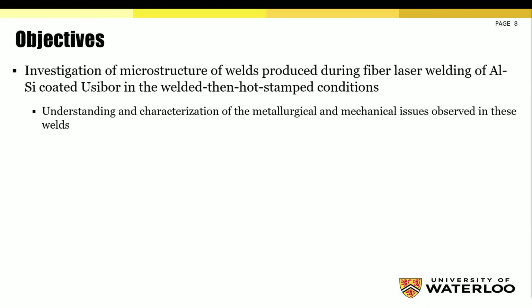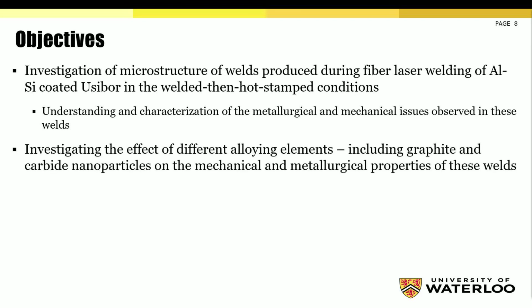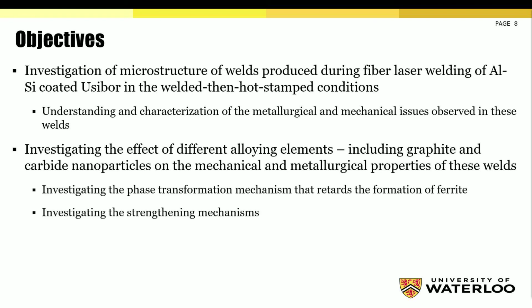So the first main objective of this research was to investigate the microstructural welds produced during fiber laser welding of aluminum silicon coated 22 Mn B5, while characterizing the metallurgical and mechanical issues observed in these welds. The second main objective was to investigate the effect of colloidal graphite and carbide nanoparticles on the mechanical and metallurgical properties of these welds. Specifically, we will be investigating the phase transformation mechanism that retards the formation of ferrite with the addition of graphite and carbide nanoparticles, while simultaneously investigating the strengthening mechanism promoted by the addition of carbon-based nanoparticles.